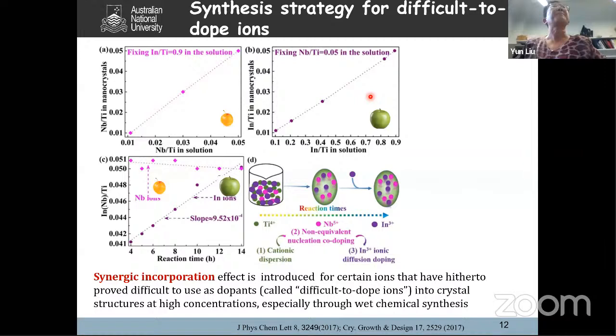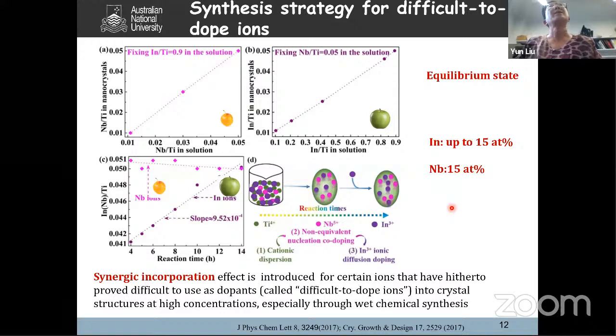So you do have niobium during the reaction come to the structure first, and then they create the environment and attract more indium to reach the equilibrium state. This is most important if you're going to synthesize: we need to reach the equilibrium state. As a result, because niobium takes indium into the materials, the indium doping level can be much higher.